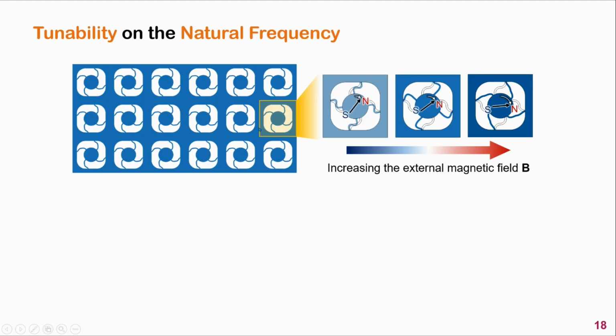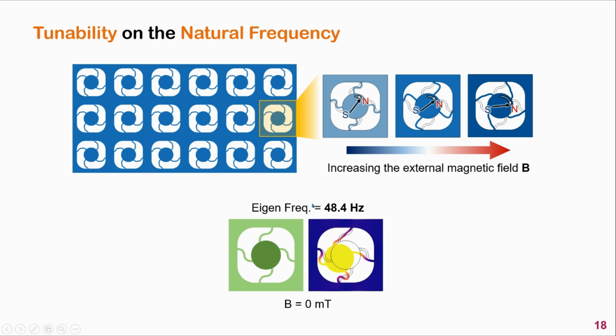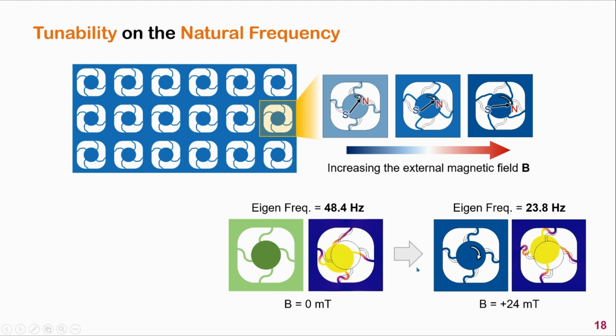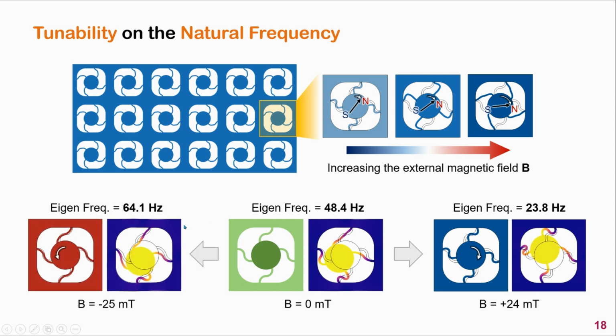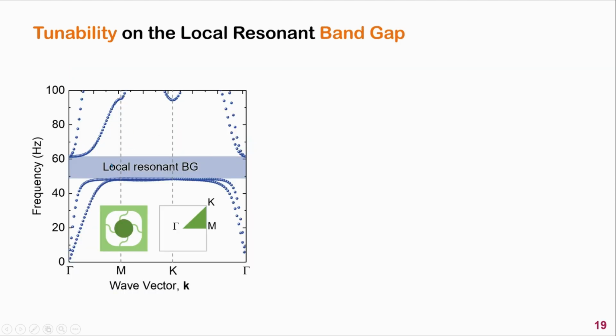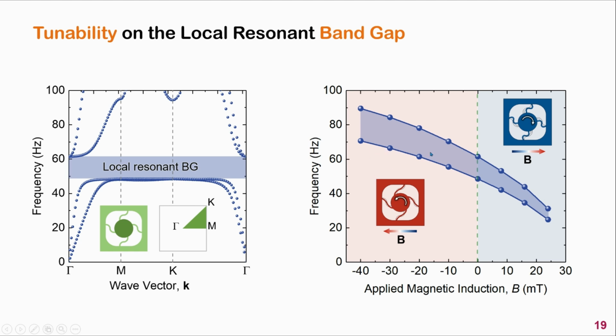For the considered local resonant metamaterials, the unit cell has a local resonant state, and this is its first natural frequency. When we apply a magnetic field in the positive x direction, the curved beams will be compressed. Its stiffness reduces, and correspondingly, the natural frequency reduces. By contrast, when we apply a magnetic field in the negative direction, the curved beams will be stretched, its stiffness increases, and therefore the natural frequency increases correspondingly. In this manner, we can tune the local resonant bandgap. This is the bandgap originating from the local resonant effect, as seen here. Both the width and the frequency position of the local resonant bandgap can be continually tuned under an external magnetic field.